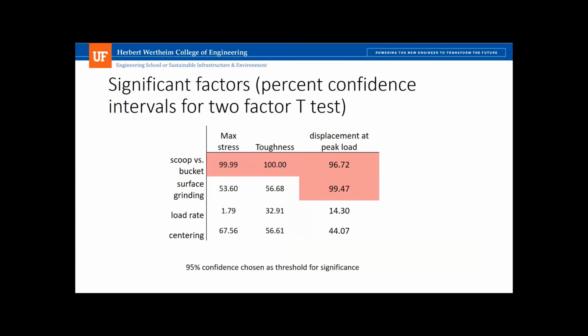So with our ruggedness test, we found that the displacement at peak load was significant if you didn't grind the samples, and that makes sense because you have to locally crush the sample at the surface in order to really dig in and seat the punch.